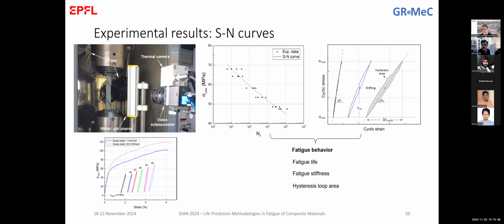I was also trying a similar experiment with the thermal imaging camera on UT Composites while doing the fatigue experiments, but I could not get the temperature rise. The temperature rise was around 2 to 3 degrees only there. I agree with you. It's not easy to do this kind of test and keep temperatures at ranges that are reasonable and acceptable for justifying that the results are not falsified.